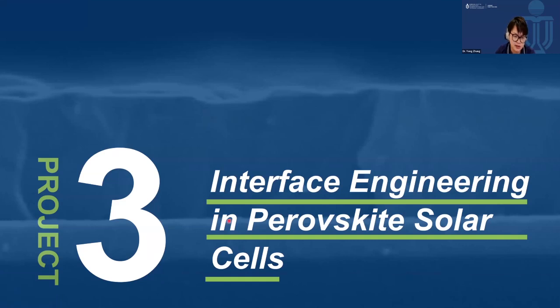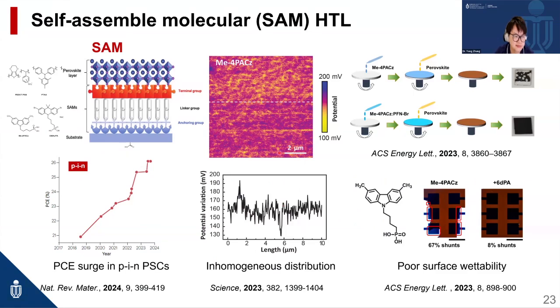The third project is interface engineering. Interface engineering is very important for achieving high efficiency perovskite solar cells. Especially the emergence of self-assembled monolayer, SAM, is very important for the inverted structure. They've boosted the PIN structure to over 26%.